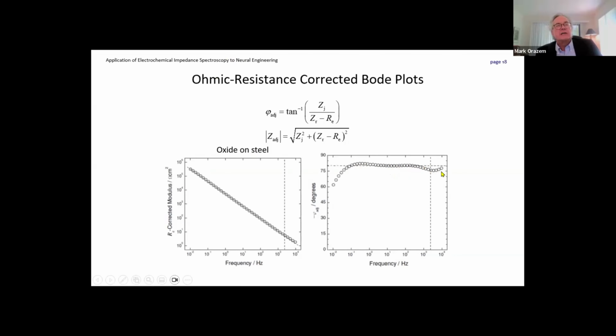What we're seeing also is that at higher frequencies, we're seeing a little bit of a dip. This is something that we very often see when the geometry of the electrode starts to influence the impedance. And we refer to this as the ohmic impedance. And the characteristic frequency corresponding to this dashed line is inversely related to the radius of the disk electrode. We will talk about ohmic impedance more later.